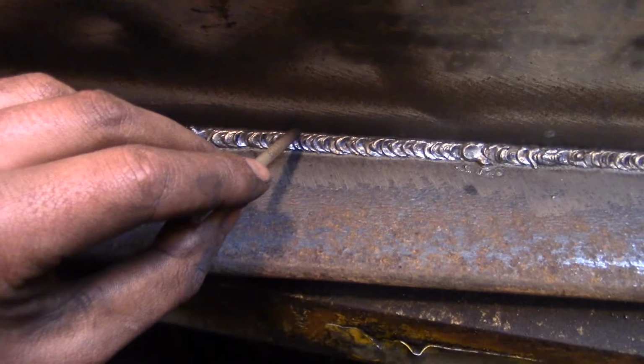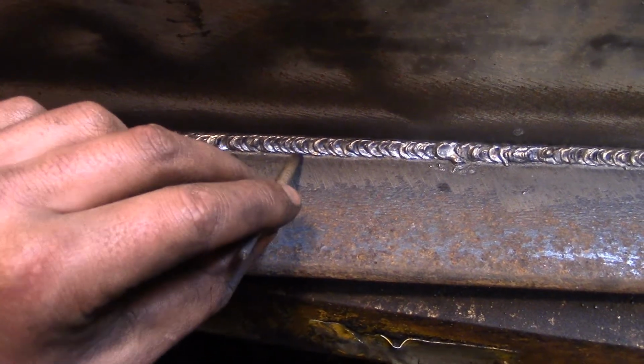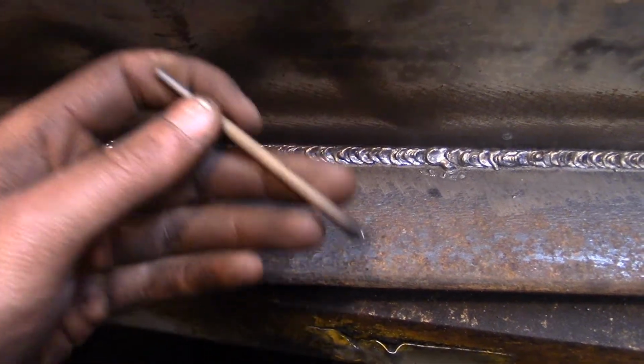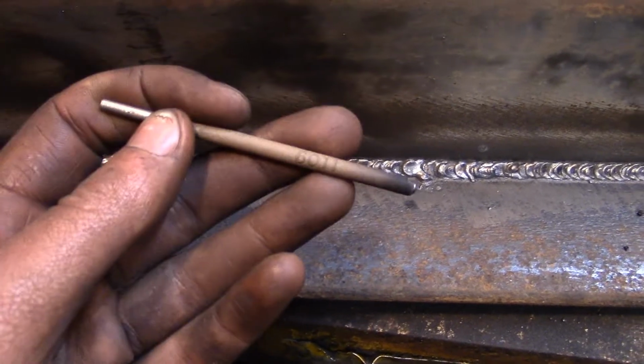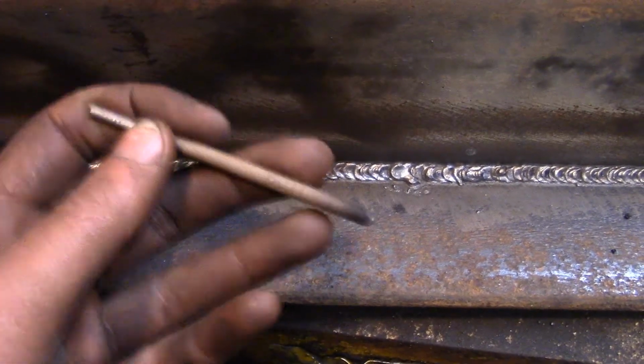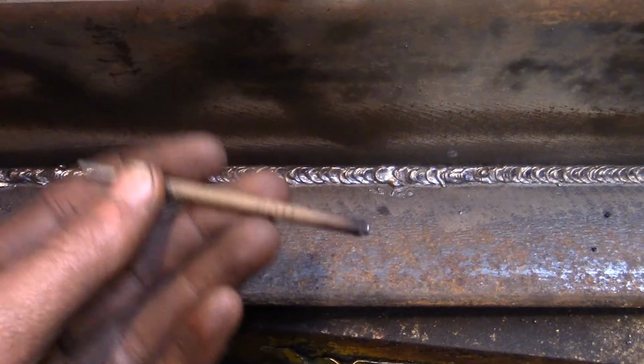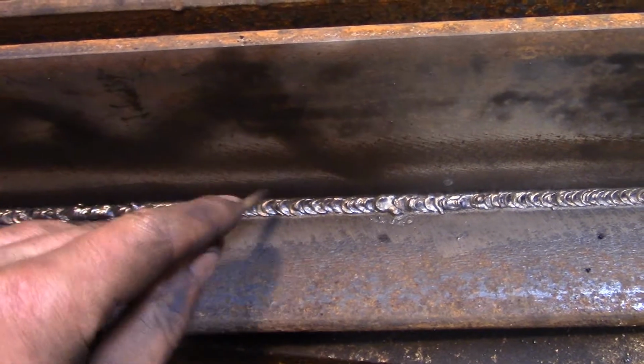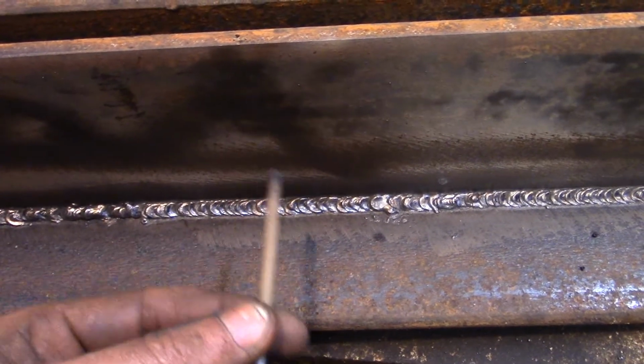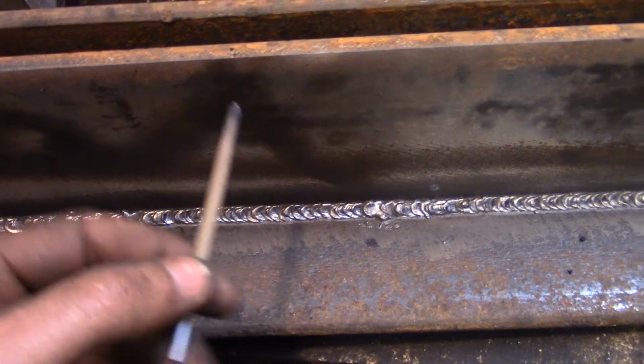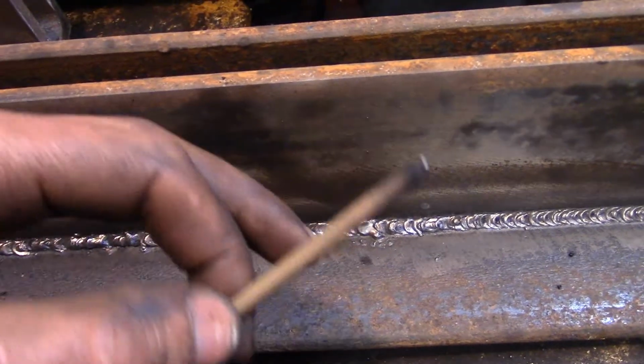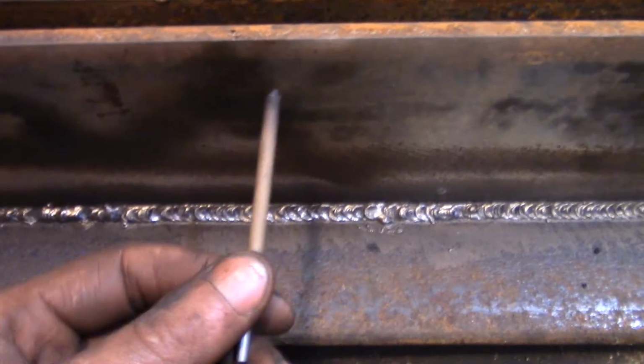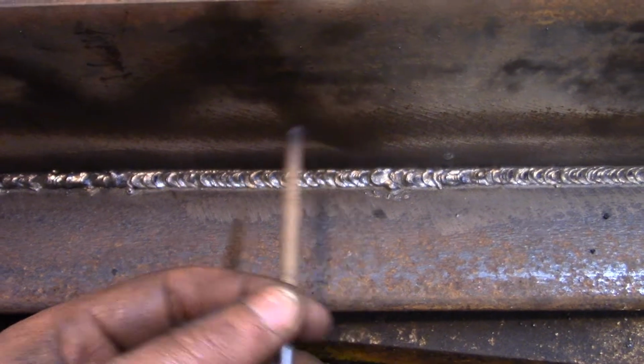One last trick. I mentioned the whip and pause earlier, and in my opinion that's the best technique to use for 6011, because 6011 is a fast freeze rod. Oh, that's another reason I like 6011, is because you can weld overhead or vertical, and the molten metal freezes really fast, so it doesn't have time to sag or drip off or get all gloobery. Yes, gloobery is a word.